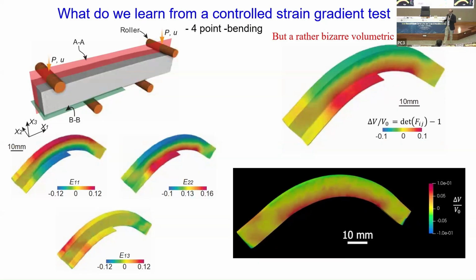Now, it's clear that this is a problem. This is a problem because if you believed rubber elasticity, this is telling you that I'm going to get a negative bulk modulus, because we know that on the compressive side, the stresses have to be compressive, which means that if the volume is increasing, I'm getting a negative bulk modulus. And silicone rubber, we can hold it in our hands, we can play with it. It's a perfectly stable material. It doesn't have any negative moduli. So there must be some other physics happening here which we have missed, which is what we now need to investigate.